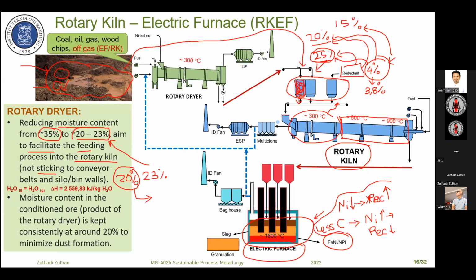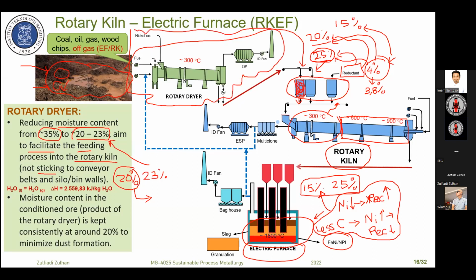And if you want to sell the products to the buyer, it's very difficult because today you produce nickel content 15%, tomorrow you produce 25%. The product is not stable, and because of that, we should control this by drying. We should control the product. In order to get a stable product, we should make sure that the drying process occurs very well. We should control the dryer.